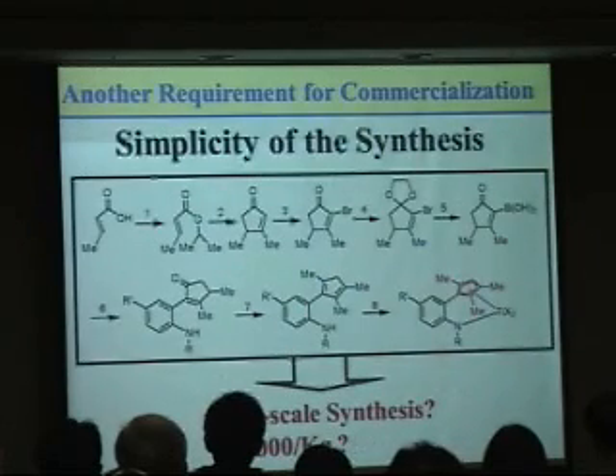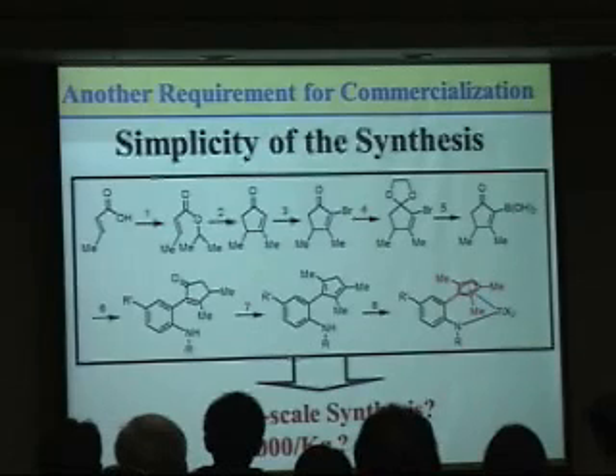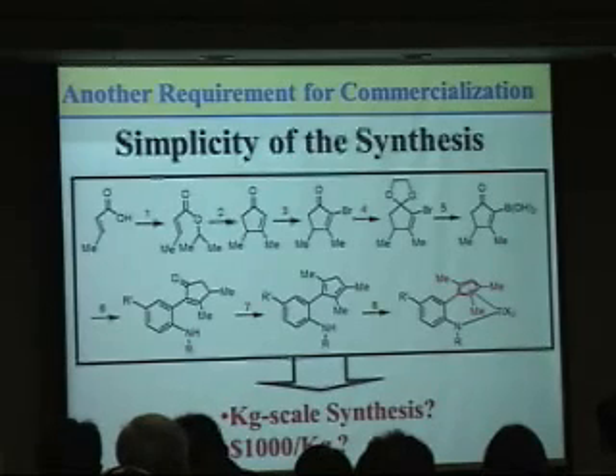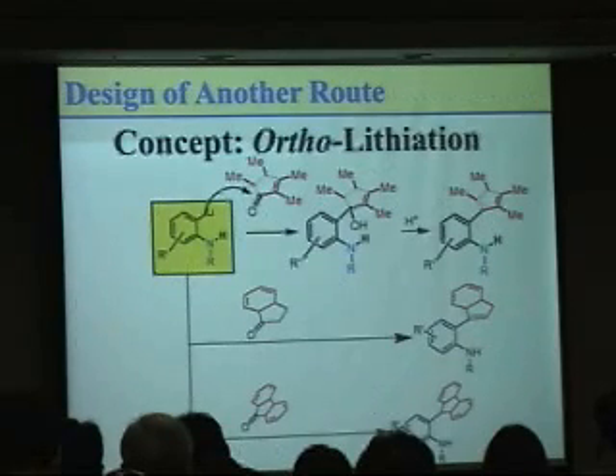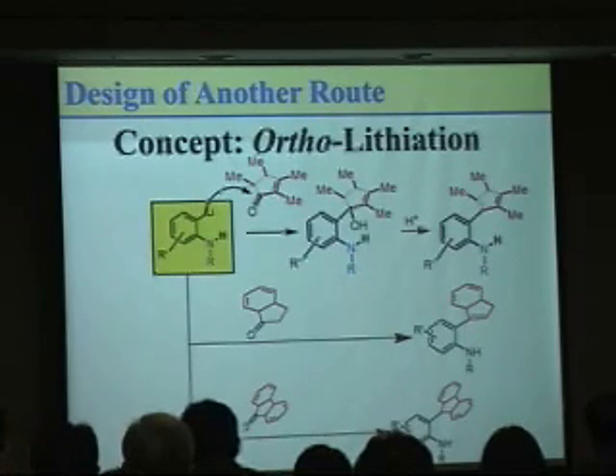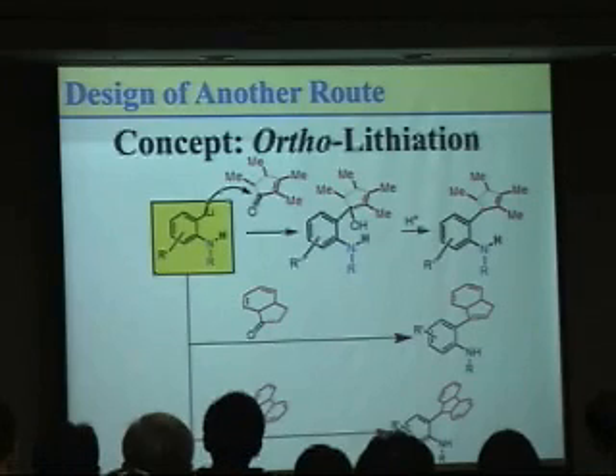But when we consider commercialization, it has a problem. We should be able to prepare the catalyst on a kilogram scale at a price of, I think, $1,000 per kilogram. But in order to prepare this compound, 8 steps are required, so we cannot make a successful story using this route. So conceptually, if we have this ortho-lithiated aryl lithium compound, the nucleophilic attack and the acid workup provide the desired ligand in just one step.